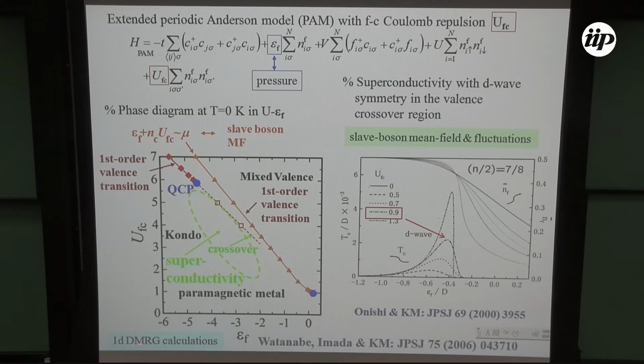This is a much more solid calculation, a one-dimensional DMRG calculation shown in this paper. For mean field, the first order valence transition curves end up with a critical point. By using the one-dimensional critical fluctuation, this point changes here, but the similar aspect is preserved. Interesting is that superconducting tendency dominates over SDW and CDW in this region, the Kondo regime near the crossover line. So it is consistent with superconductivity appearing near this critical value of epsilon f.